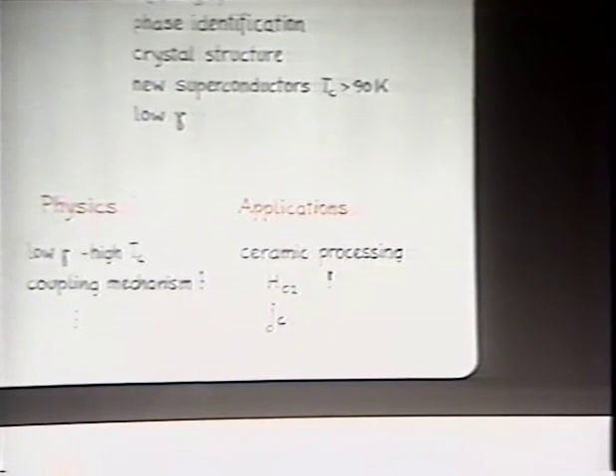One is the physical aspects of it. We are having low gamma materials, very high TCs, and we certainly have to think about new mechanisms, at least think about them. That's one way I think we are all glad working in this field. The other thing is that, as I just tried to convey a little bit of a flavor of it, it might be quite possible that, due to the fact that these are ceramics, we have high upper critical fields and not so discouraging values for the critical current density, which might lead us to potential applications a few years from now, and I think our life has changed. Thanks a lot.